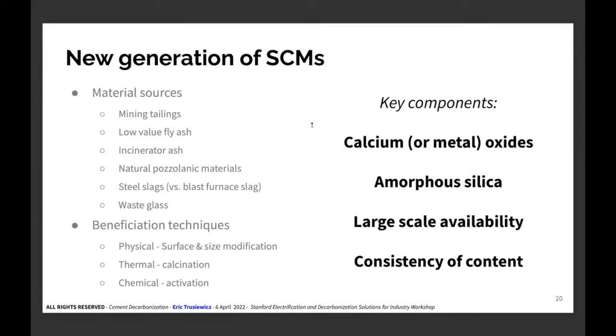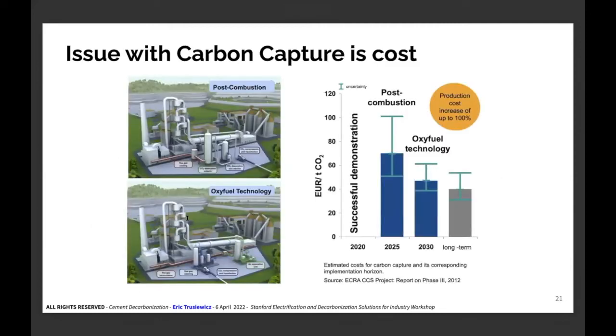And if they have some amorphous silica fraction, or if they have a reactive metal oxide in it, or if you can beneficiate it so you have a homogeneous and cheap material that has that, that's really good. And actually, electrification has a really interesting potential application in the thermal beneficiation of some of the emerging SCMs, especially calcined clay, I think, because that happens at a temperature where electrification makes more sense. So that's SCMs, both traditional and emerging.